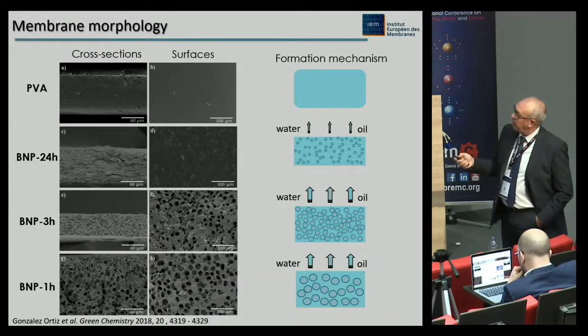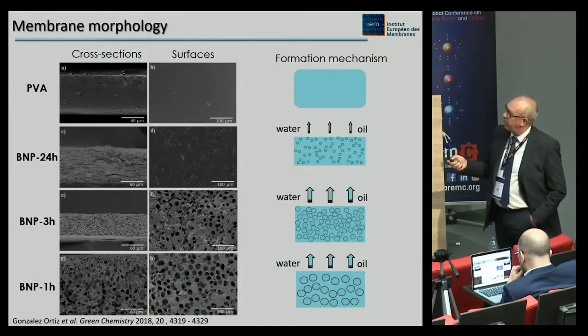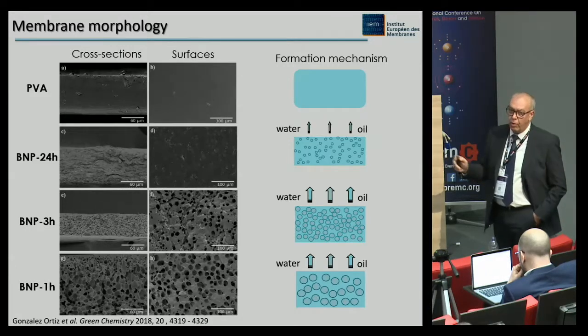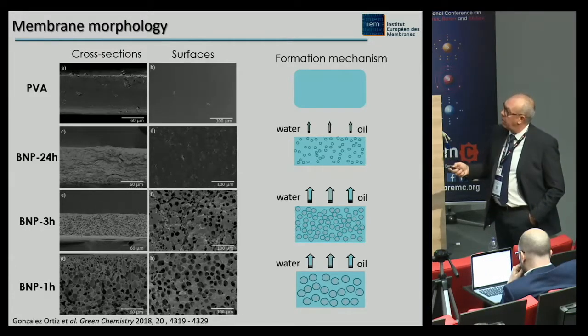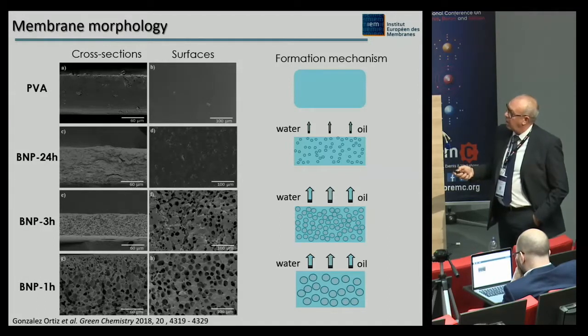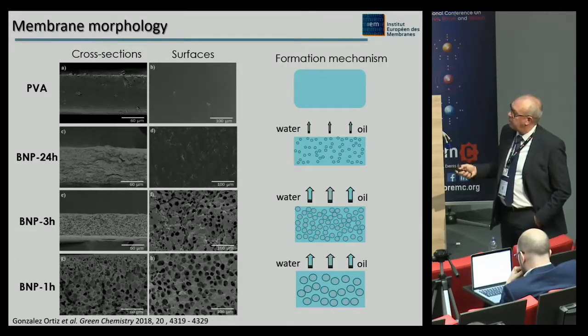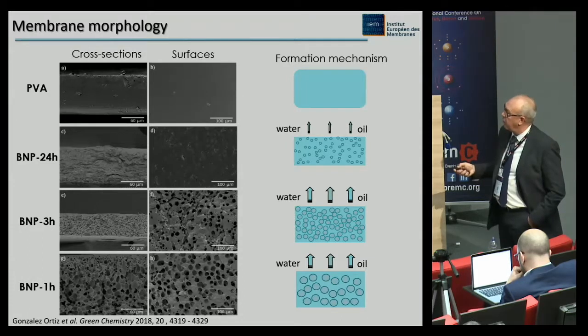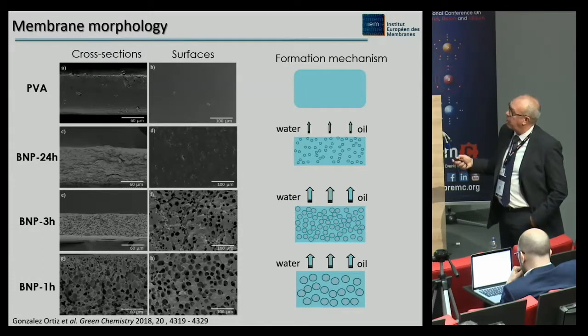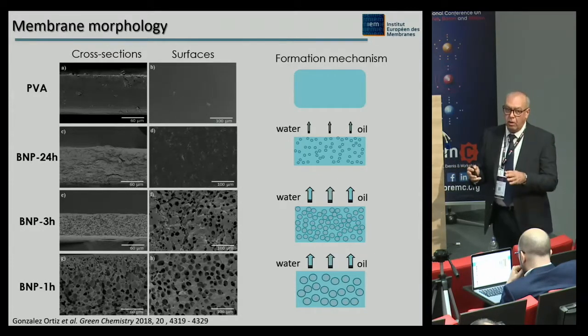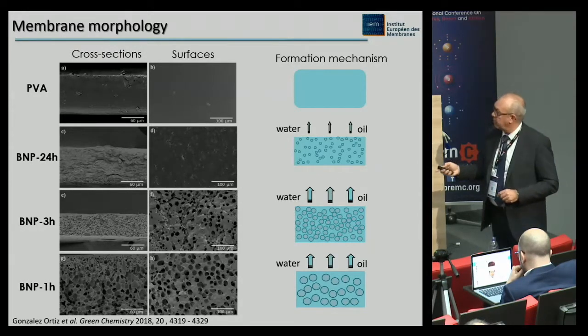So here are the membranes, with the PVA membrane alone with no porosity, the BNP prepared after a curing time of 24 hours, and these two membranes with a curing time of 3 hours or 1 hour. So, as I said, the curing time is necessary to remove the water and oil, and this method can be used to tailor the porosity of the membranes.